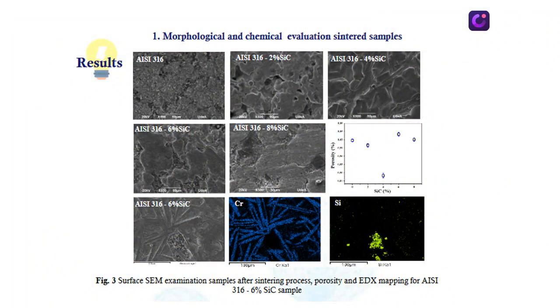In the results, we can observe the microstructures of the steel samples and their different additions. For the AISI 316 sample, a microstructure of fine grains and oxide roots is observed, and very noticeable microcracks throughout the surface after the sintering process. In the case of the sample with 2% silicon carbide, oxidized and porous areas, and areas that formed necks were observed, showing the formation of micrograins.